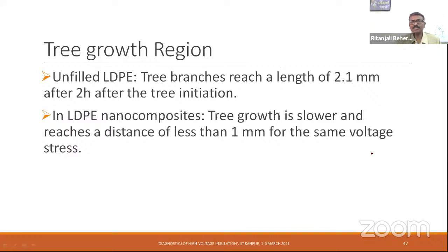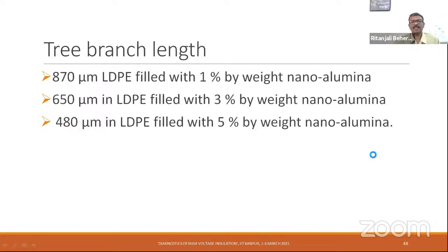Tree growth region. In the unfilled LDPE, the tree branches reach a length of 2.1 mm after 2 hours. This is after tree initiation. Whereas in the nanocomposites, it reaches only less than 1 mm for the same voltage stress, thus prolonging the tree growth. In fact, tree initiation is also reduced, as we have seen. The progression also is arrested. The tree branch length is 870 micrometer for this LDPE, which is filled with 1% of nano alumina, and it is reduced as we increase the filler weight percentage.